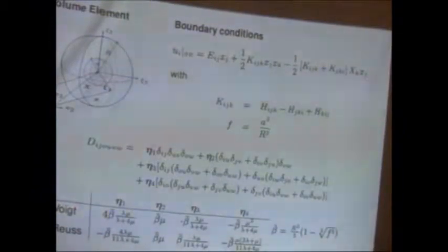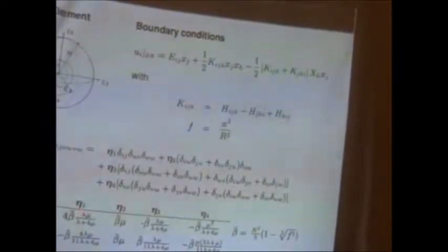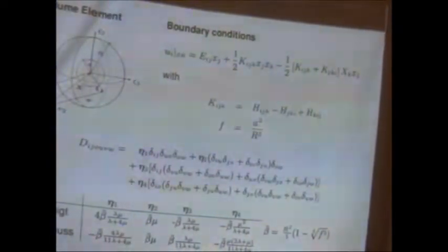But we didn't solve it in the same fashion as before; we tried to get bounds for the higher order elasticity tensor in terms of Voigt bound and Reuss bound. This was actually possible. As long as we are talking about isotropic behavior, we have an isotropic 4th order tensor as in general elasticity. In addition, we have an isotropic 6th order tensor which relates the higher order stresses and the strain gradients. An isotropic 6th order tensor usually has 5 independent parameters. It turns out, if we apply this kind of homogenization procedure, this reduces to 4 independent material parameters, given here by eta 1 to eta 4.